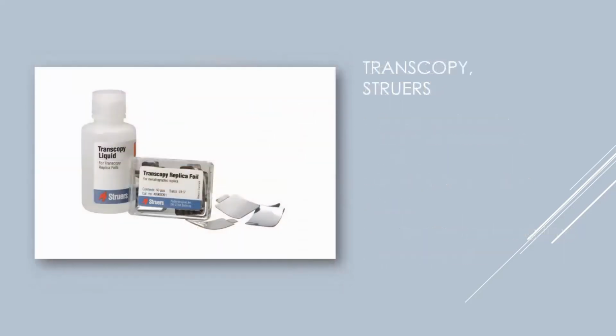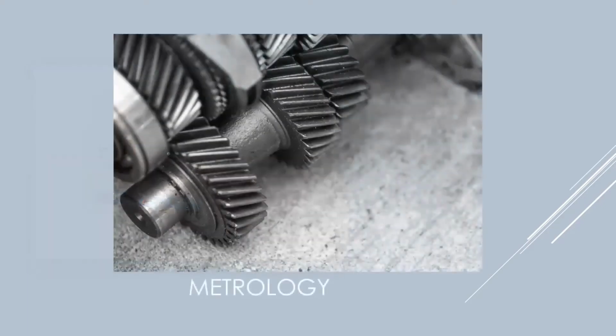This is the Struers Transcopy, and what they do is it's still cellulose acetate, but they have a reflective background on the back to give you better contrast, because that's one of the unfortunate things with cellulose acetate: we have very little contrast because it's clear, and this will help you out a lot.